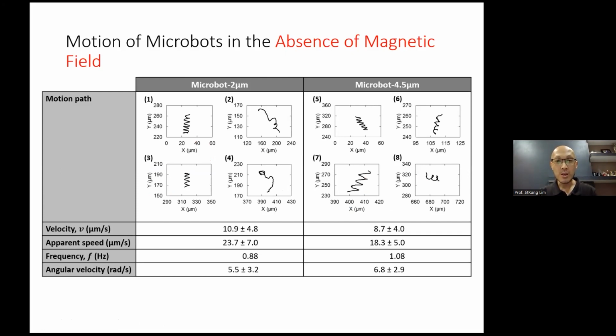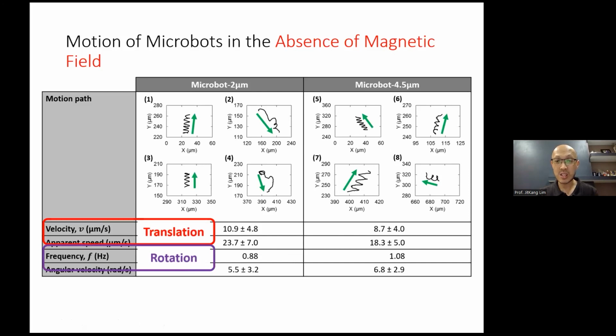And if you really look at it, since we constructed the microbot using 2-micron particles and also 4.5-micron particles, you can see the velocity actually reduced quite significantly. Remember the number I told you just now, 100 micrometers per second? The velocity reduced quite significantly, and the apparent speed becomes about 23 micrometers per second. And if you check, of course the translational velocity reduced, and the beads started to rotate. When the beads become bigger, the translational motion further reduced and the frequency increased, so they rotate more rapidly.